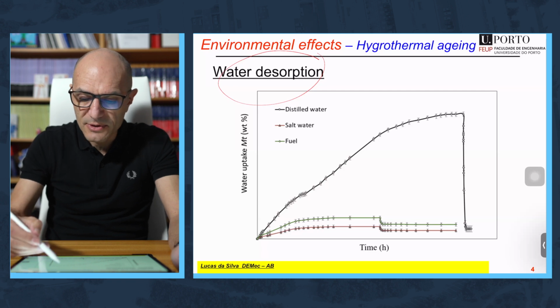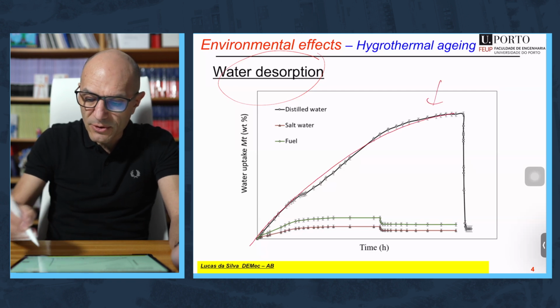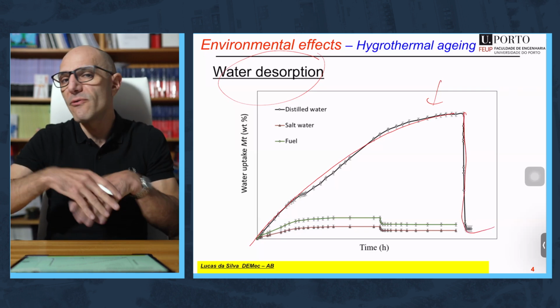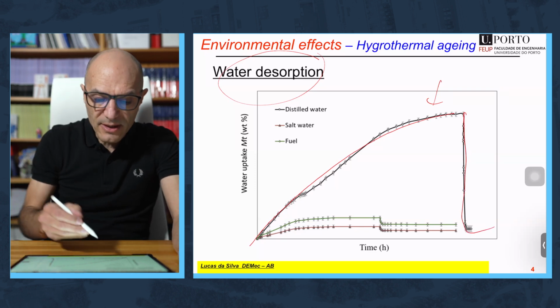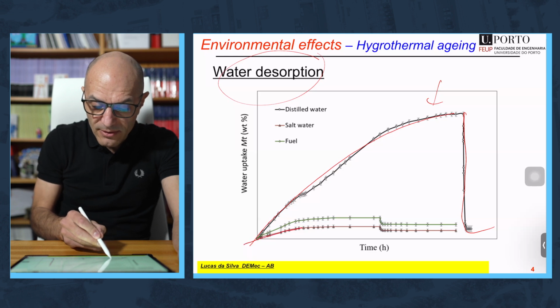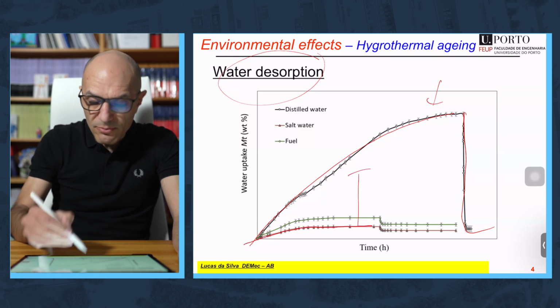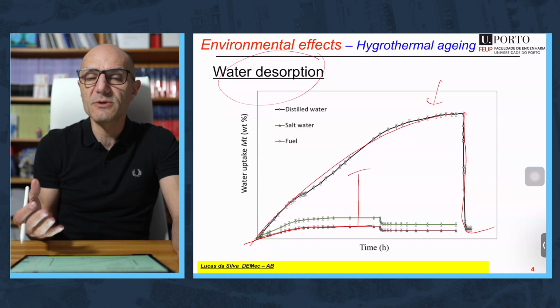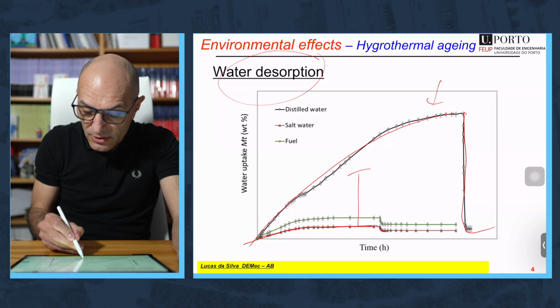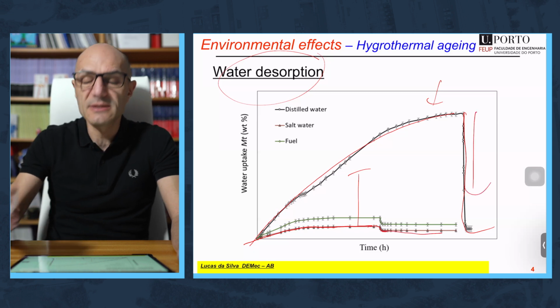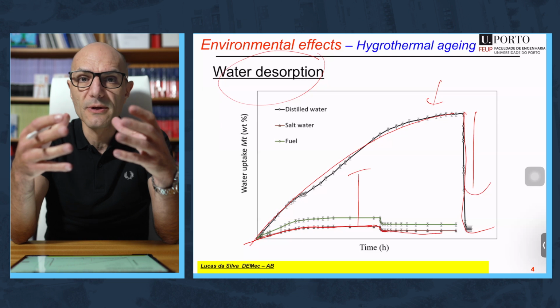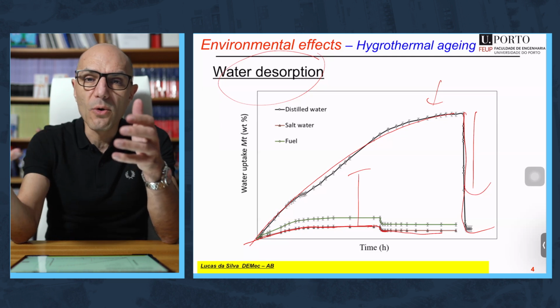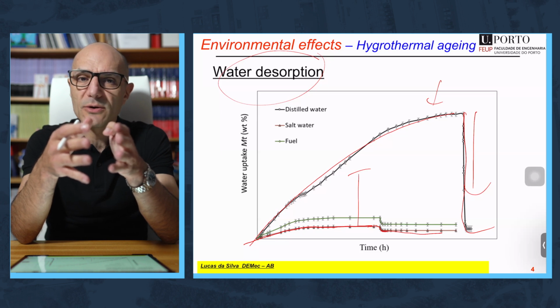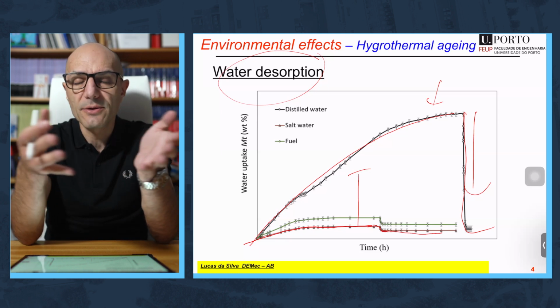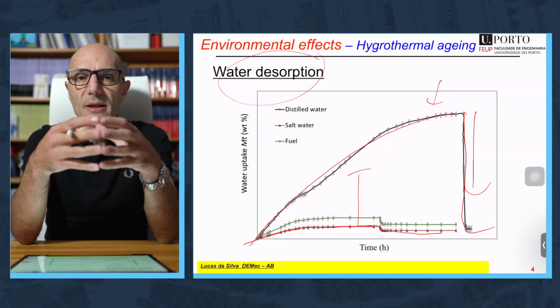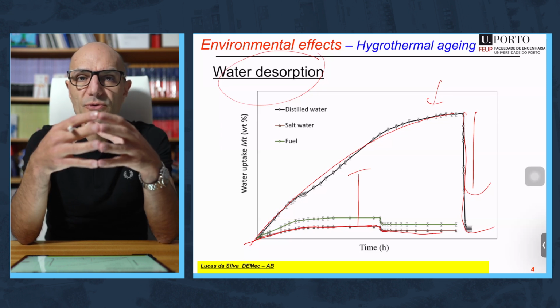Take for example the case of distilled water. This is the period of absorption, and then when you dry, you basically remove all the water that is inside the adhesive. But take the case for example of salt water. First of all, the amount of water is not comparable. The adhesive will absorb much less water, and then the desorption also will not be as much as when you have distilled water. This is basically due to the presence of salt. The salt will not let the water go in because it will be like a barrier, and it will not also let the water go out because it's another barrier. So this desorption problem is also important to measure.